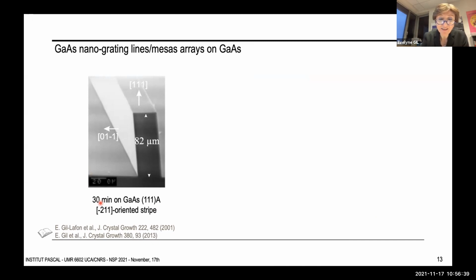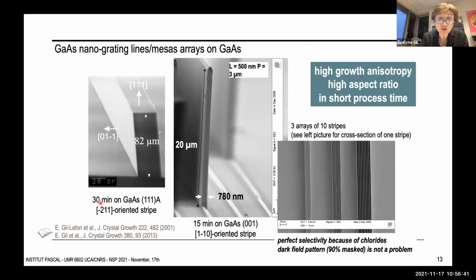And indeed, the possibility to exploit the high intrinsic growth anisotropy of III-V crystals is maintained at the nanometer scale here with the synthesis of arrays of perfect stripes presenting unusual aspect ratio in a few minutes of growth, and on a substrate which was masked over more than 90% of its area. If someone in the audience has an idea of any use of such arrays of III-V stripes, please come to me.